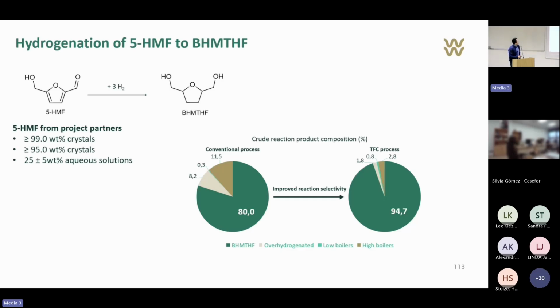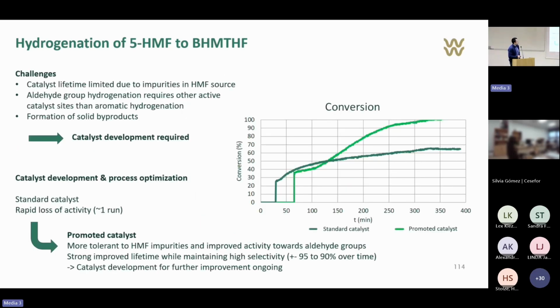So that's good, although there are also some challenges with converting 5-HMF. That is mainly related to the catalyst lifetime. We see it's much more limited compared to methyl THF production because of impurities in the HMF source. And also 5-HMF has an extra aldehyde group, which methylfuran, for example, doesn't have.